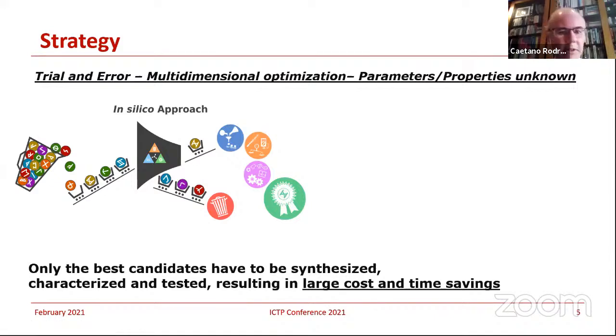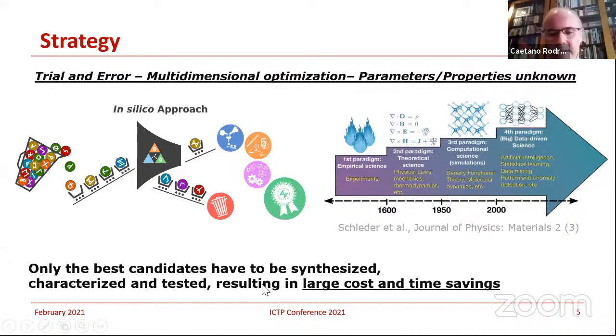So the approach that you're going to use is actually going back in time in terms of the evolution of methodologies from the scientific point of view. You're going to use machine learning methods to make a selection of potential candidates. Then you validate them with density functional theory. Then you use linear elasticity to check for real applications before actually doing the experiments on this system.